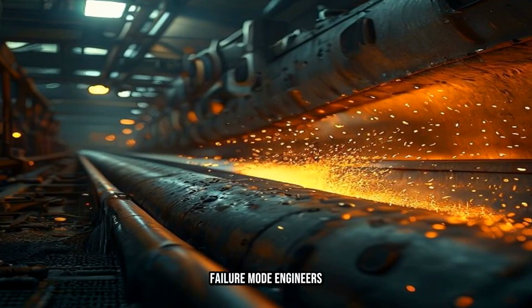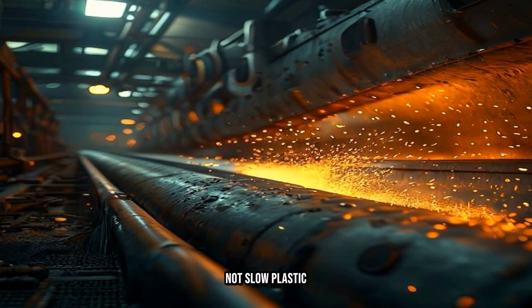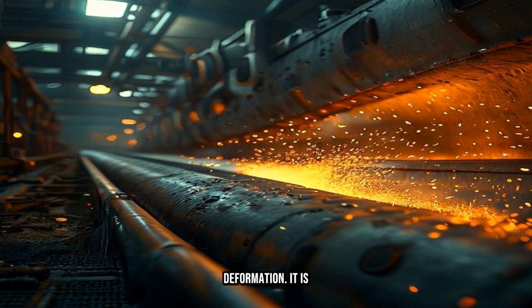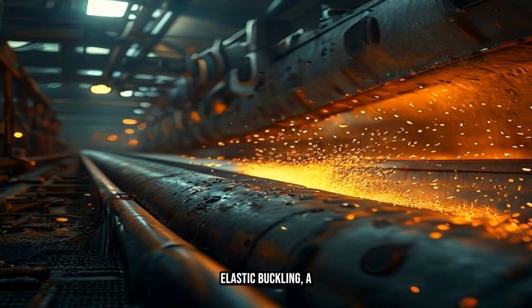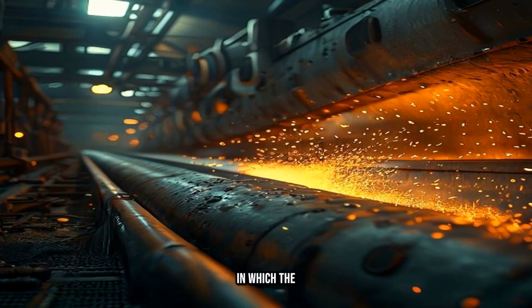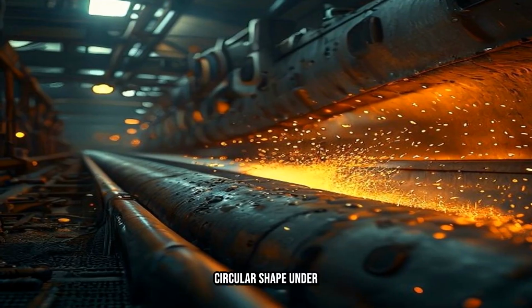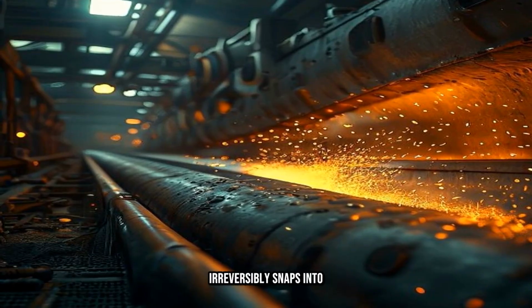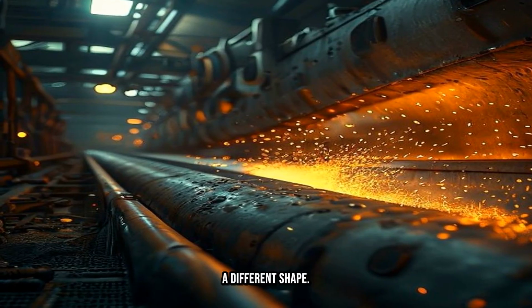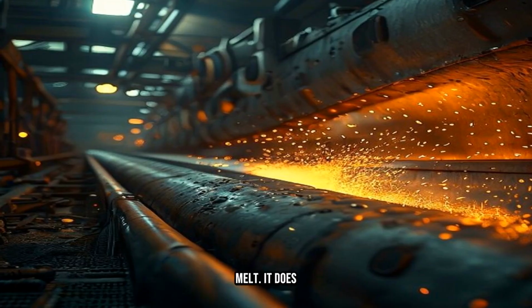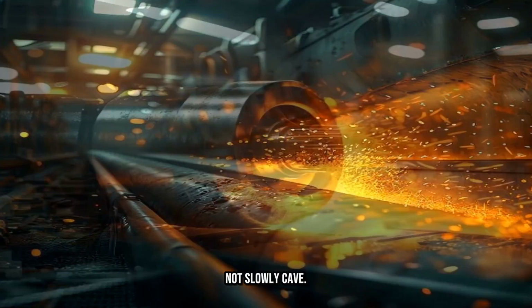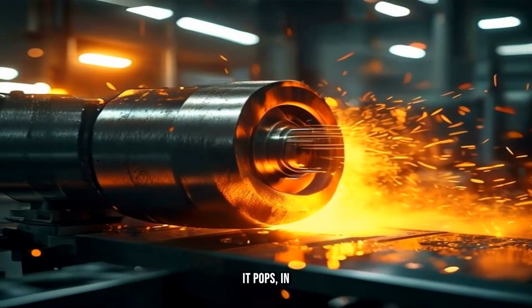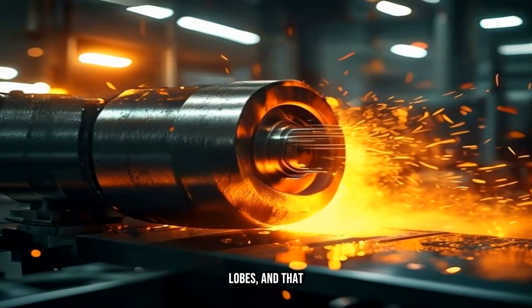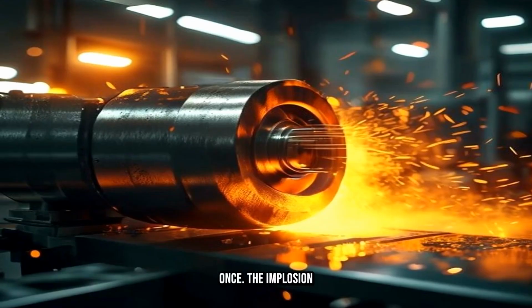The failure mode engineers most fear is not slow plastic deformation. It is what they call elastic buckling, a sudden geometric instability in which the hull, which has been holding its circular shape under compression, abruptly and irreversibly snaps into a different shape. It does not melt. It does not slowly cave. It pops, in a fraction of a second, into an oval or a series of lobes, and that geometric change releases the stored elastic energy all at once.